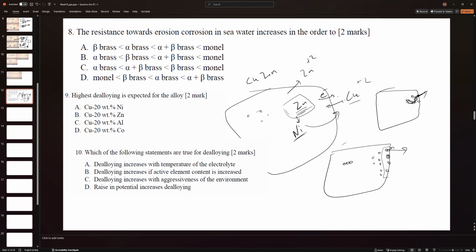In an aggressive environment, your dealloying should increase. So if you lower the pH, increase the Cl minus concentration, it promotes dealloying. And increasing the potential also increases dealloying. Yes, one should be fine.